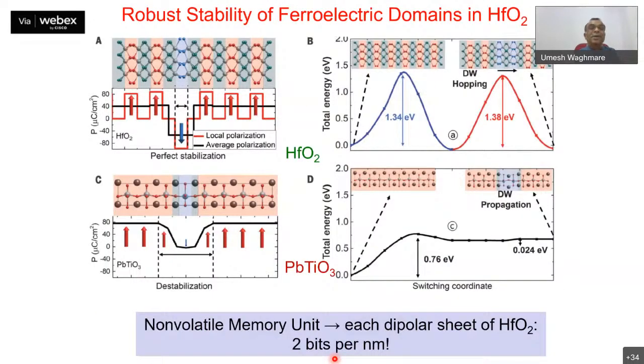What is more spectacular is you can switch one oxygen sheet down with dipole moment down, and it has exactly the same energy as the uniform polarization, and it passes through a huge barrier. So if you have one dipole switched or two dipoles switched, you see two sheets of electric dipole, you have the same energy, which is separated by a large energy barrier. This is very different from barium titanate or lead titanate, where if I try to switch one dipole moment, you know, it spontaneously goes into a much bigger domain. And that's the domain wall, which brings up and down polarization.